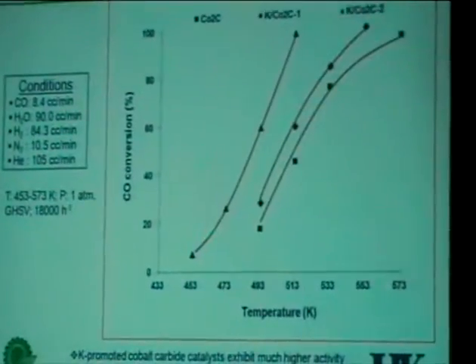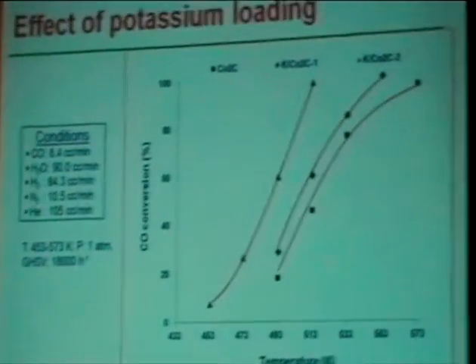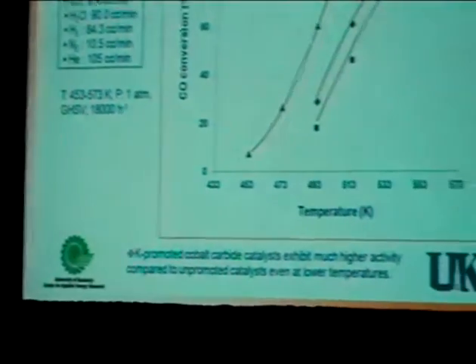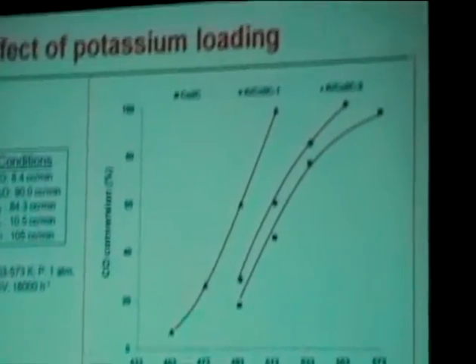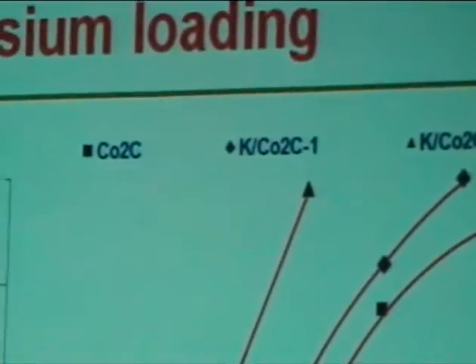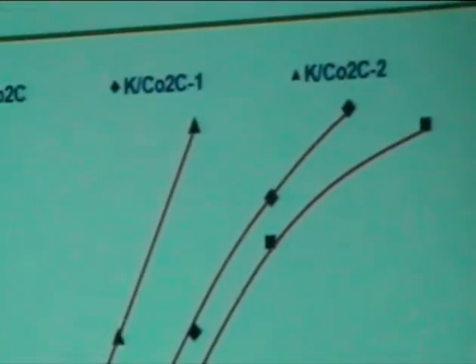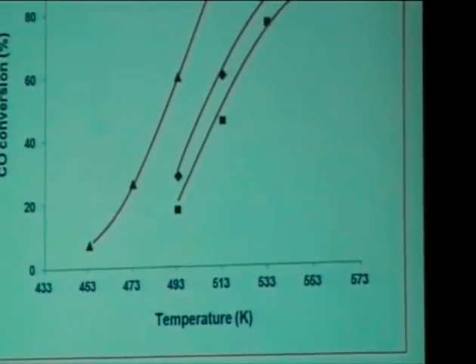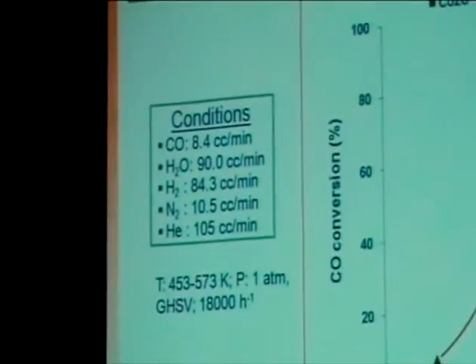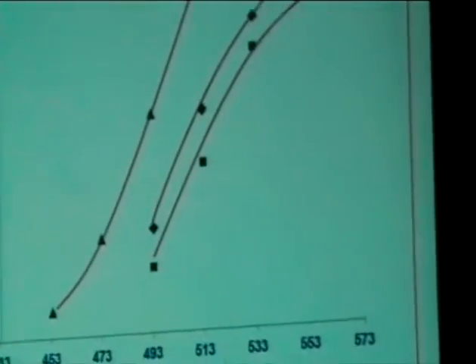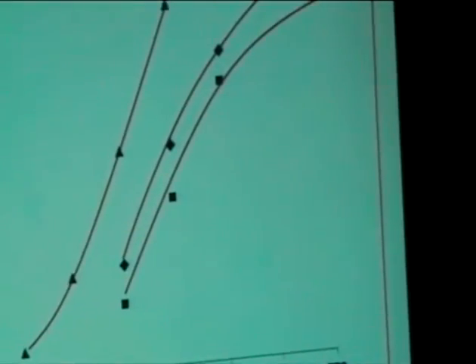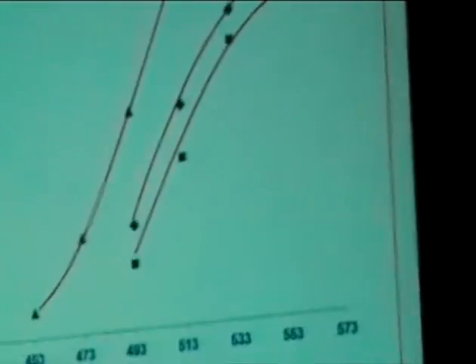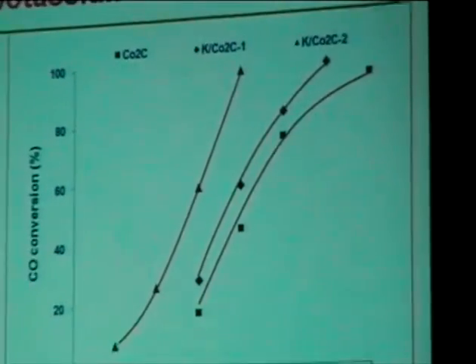And so here we are comparing the effect of potassium loading. As you see, the square one shows the cobalt carbide, and the potassium promoted one is showing higher activity compared to this one. The effect of loading clearly indicates that potassium is influencing the water gas shift activity by promoting the carbide formation.